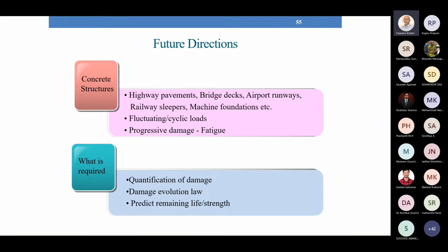And the future directions: we all know that concrete structures such as highway pavements, bridge decks, airport runways, railway sleepers, machine foundations, all of these are subjected to fatigue loading, cyclic loading, wherein progressive damage takes place. Now we have established through the acoustic emission that the damage process is progressive. It takes place very slowly, but a final failure occurs due to the release of a large amount of energy. So what is required is we have to quantify damage. First, we have to define damage, then quantify damage in structures which are under service, use the damage evolution law and predict the remaining life of the structure. So this is what is required, which we are working on.